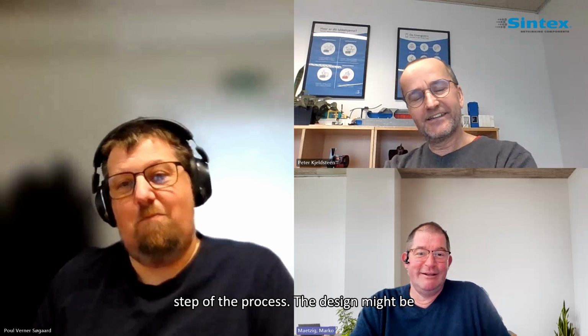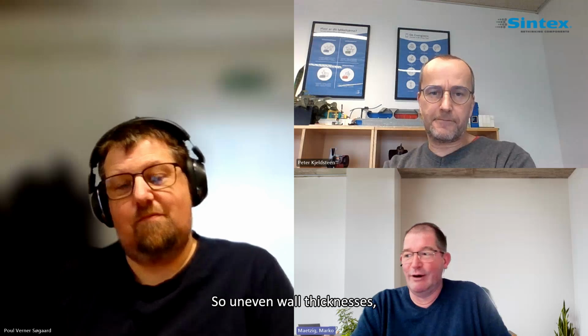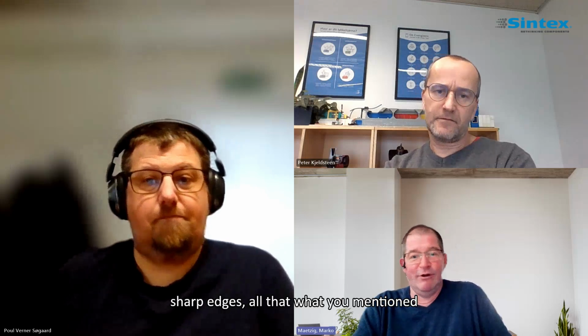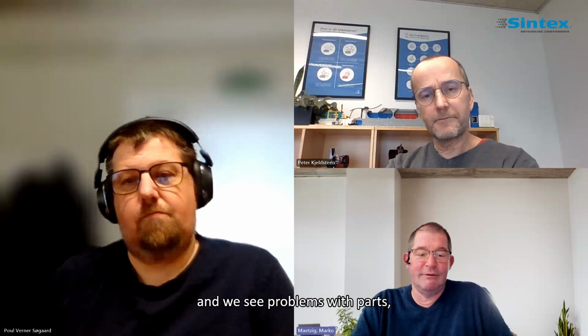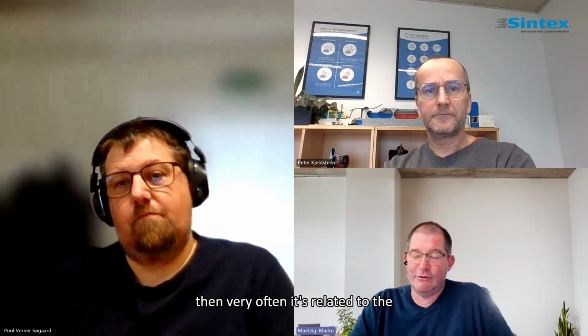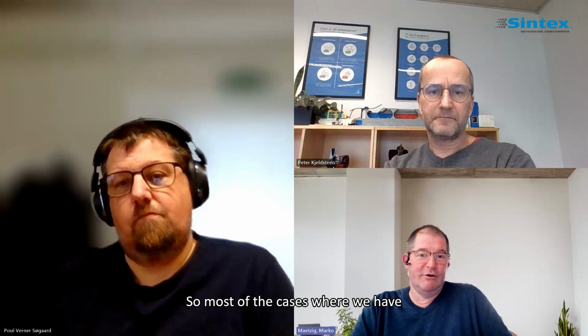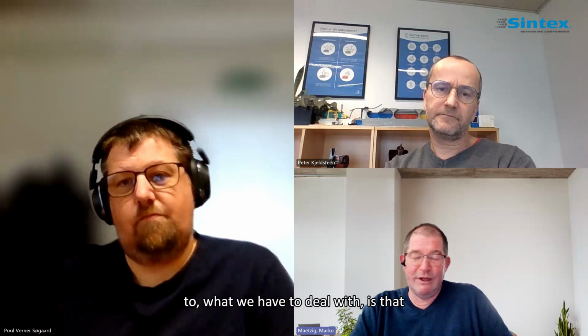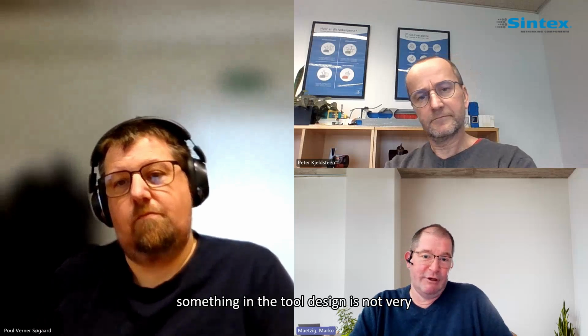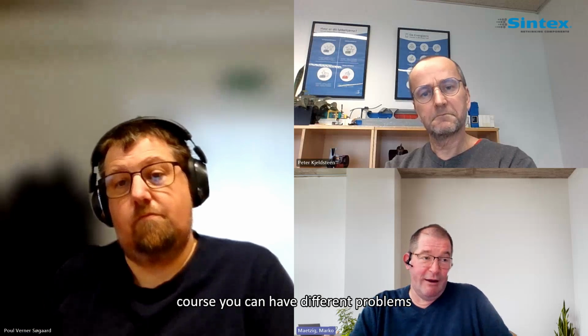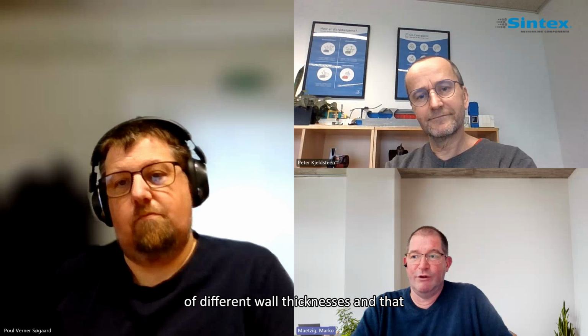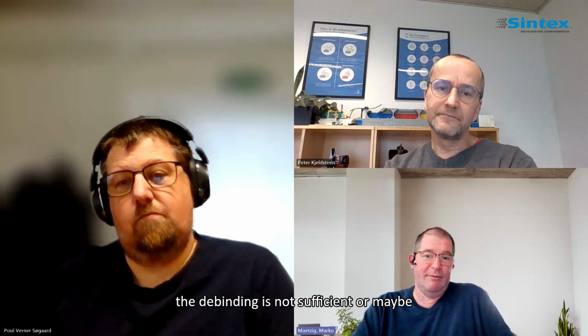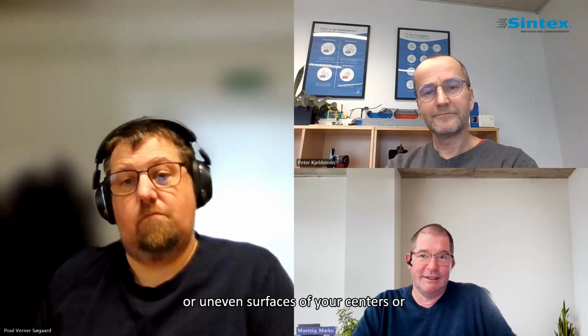That's the interesting part. Basically, you can make mistakes in every step of the process. The design might not be very good from the beginning, so uneven wall thicknesses, sharp edges, all that you mentioned before. But when we look at parts with problems, very often it's related to the design of the tool. Most of the cases we have to deal with are where something in the tool design is not very well chosen. And of course, you can have different problems also in the post-processing steps because of different wall thicknesses, so that the debinding is not sufficient, or maybe distortion during sintering because of the mentioned center of mass problems or uneven surfaces of your setters or whatever is possible.